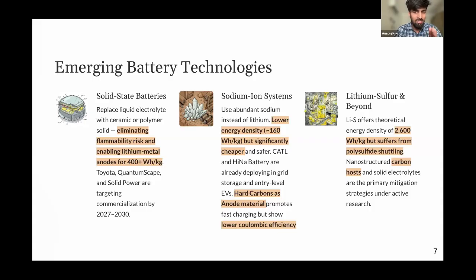Now, using just sulfur, during the discharge reaction the sulfur gets changed. Structural changes happen when sulfur alloys with lithium, and it makes certain polysulfides. These polysulfides are liquid in nature and they dissolve in the electrolyte. If they dissolve, then it is nothing but loss of capacity. And these polysulfides shuttle between the anode and the cathode. Lithium is an active material, so we are losing all the lithium because it has converted into passive lithium polysulfides, which cannot be